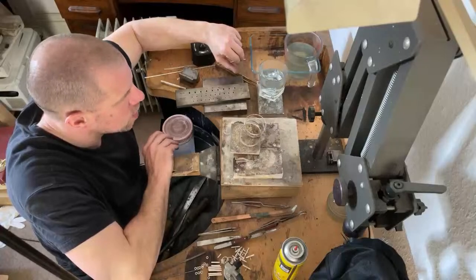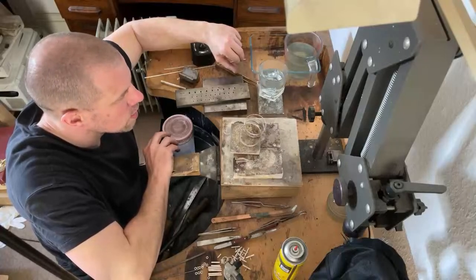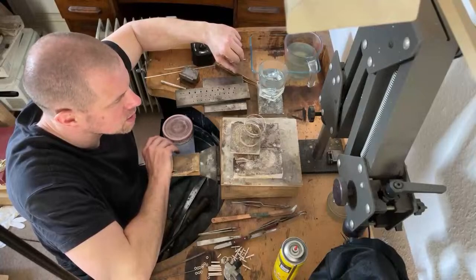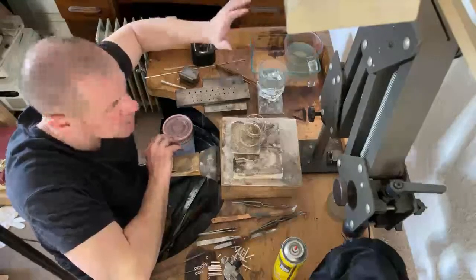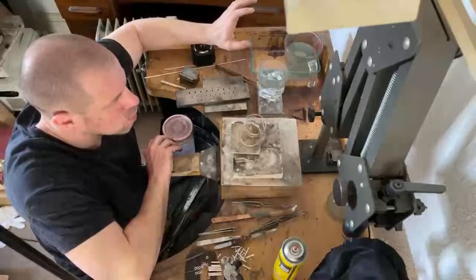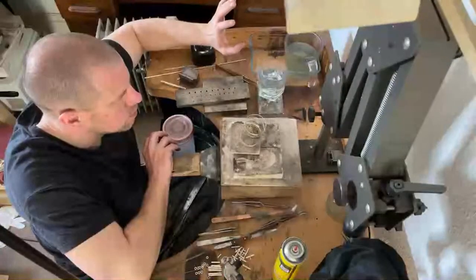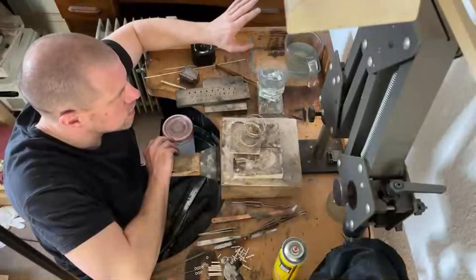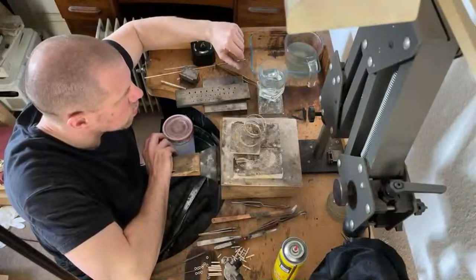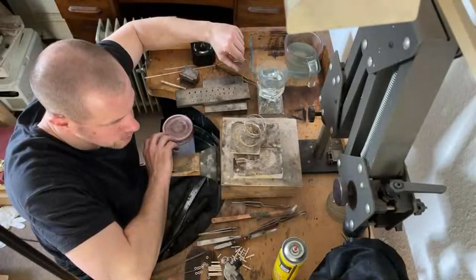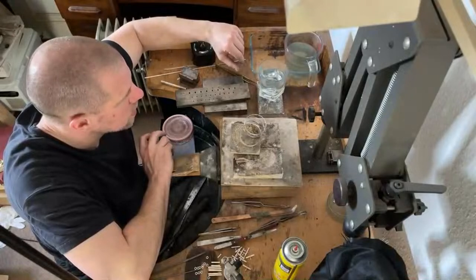Quenching silver, I was ending up with subsurface water. When I was rolling it out, it was almost like wringing out a sponge, which is a bit of an exaggeration, but you would get water on the rolling mills. The water would be subsurface, it would come out, it would blister as well, and it definitely caused cracking. It was quite soft and workable, but quenching it caused problems.